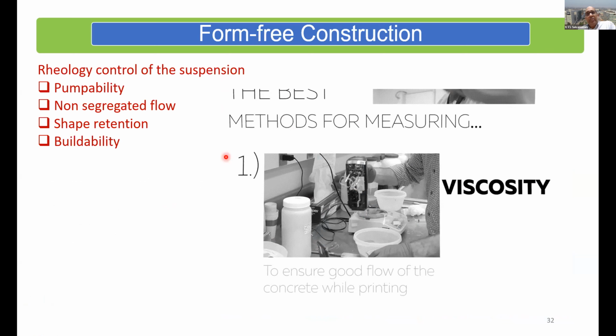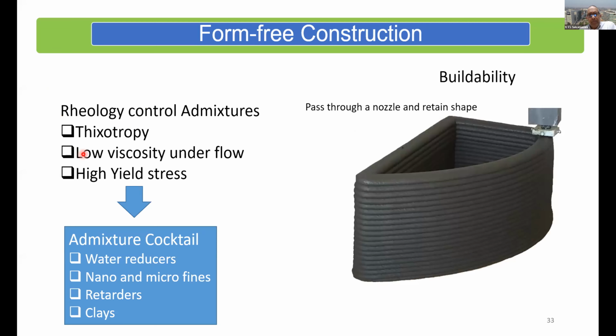Then now we are coming into the domain of form-free construction, which is taking us into 3D printing. Now we expect mixtures which are 3D printable to have 3 or 4 essential properties. It should be pumpable. I should be able to pump the concrete. It should have a non-segregated flow. As I'm pumping, it should flow like a uniform mixture. It should have shape retention. When it comes out of the nozzle, it should keep the shape of the nozzle, and it should be buildable. I should be able to stack multiple layers and build the entire structure. And that again brings us into rheology control with the use of admixtures.